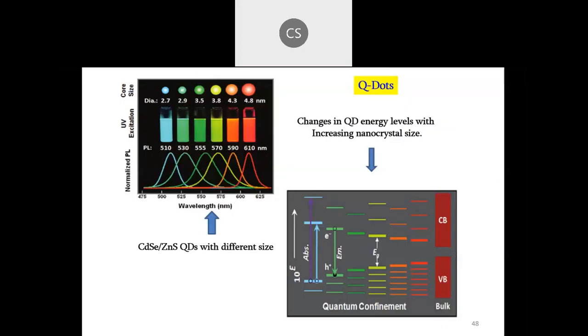So you can see the peculiar behavior of quantum dots. This is an example of cadmium selenide zinc sulfide based quantum dots with different sizes. You can see at the top the diameter of this particular molecule varies only from 2.7 to 4.8, that is, approximately only 2 nanometers of variation in size. But with each variation, like 2.7 to 2.9, you can see the color changes and the corresponding photoluminescence value varies from 510 nanometers to 530 nanometers. So this is the reason why this quantum dot based material shows a different color based on its size. You can see this is the 4.8, the red one, and this is the 2.7 in blue color.